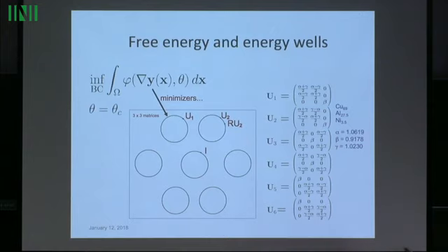So the way you should think about this is there's a surface phi which comes down and touches the slide at exactly those 7 circles, and everywhere else is positive. Okay, that's the kind of free energy density which comes out of those symmetry arguments. Typical free energy density for a crystal which undergoes a phase transformation.